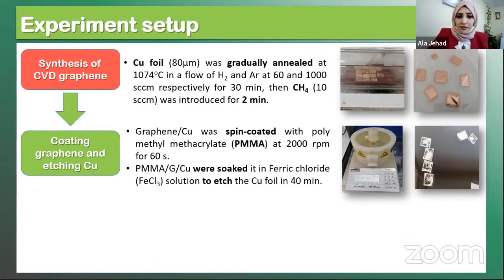And then to etch the copper foil, we soak the substrate, PMMA, graphene and copper, in ferric chloride for around 40 minutes, and then we washed the samples 3 times in deionized water, and then we transfer it on the silicon.